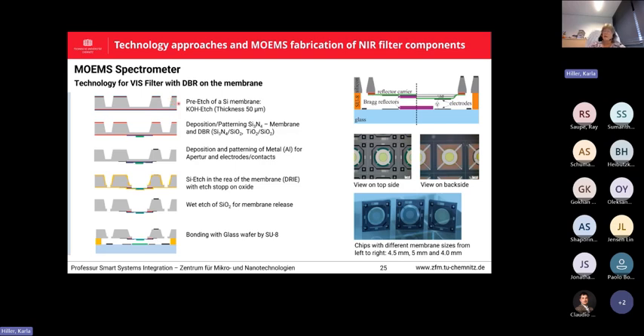As Christian already said, we start to pre-pattern the upper wafer to have the membranes of approximately 50 micrometer to save some etch time for releasing the membranes later. Then we deposit the membrane material, the silicon nitride, shown in blue. And also we deposit and pattern this Bragg reflector stack by a combination of wet and dry etching. Here we can integrate now, so it's not so complicated from the lithography point of view. That's why we could further integrate the electrodes and also contact pads to the silicon. And then comes the release etching using the dry etch process so that we have the released membranes.